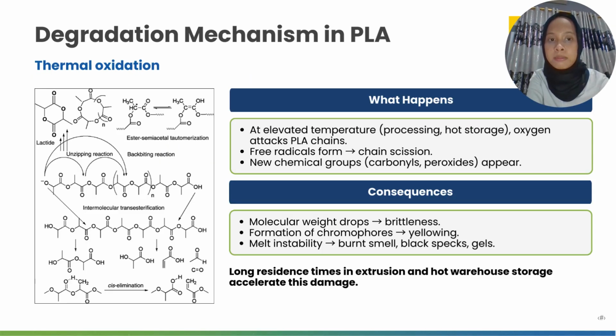The degradation mechanisms that occur because of these failures. First is thermal oxidation. What happens in thermal oxidation? Elevated temperature in processing or hot storage, oxygen attacks the PLA chain and free radicals form, causing chain scission, which means new chemical groups, carbonyl and peroxide, appear. As a consequence, the molecular weight drops and it causes brittleness, formation of chromophores, and yellowing. Melt instability leads to burnt smell and black speck gel. The key takeaway: long residence time in extrusion and hot warehouse storage accelerate this damage.